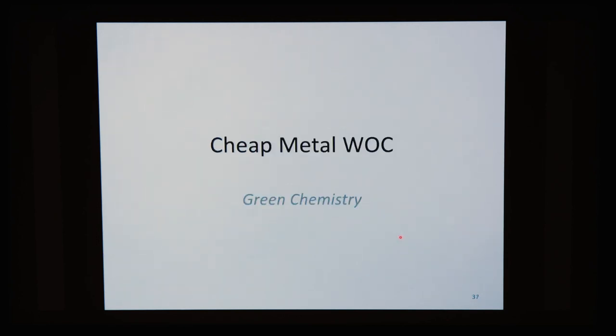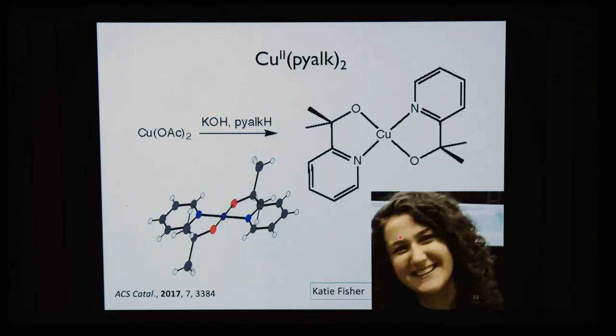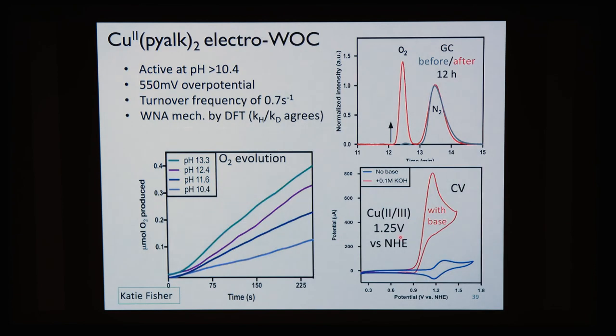Now, iridium is the most expensive, or I should say the rarest of the platinum metals. And so copper is an alternate possibility for water oxidation. And here's Katie's complex in which she takes pyalk with copper acetate and forms the bis pyalk compound. And this also is an electro water oxidation, but it's only active in basic solution. It has a 550 millivolt overpotential, so that's not so good. Turnover frequency 0.7, that's fine.